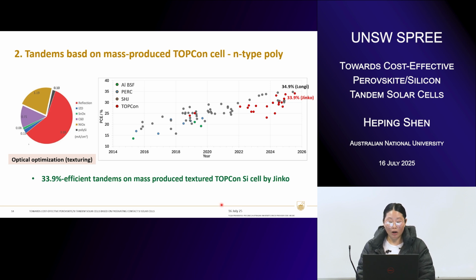simultaneously, we have been doing the optical optimization, particularly by using some texturing of the silicon substrate, majorly focusing on nano-texturing, which means texturing with a size of roughly 1 micrometer or less. For that we did a lot of work in collaboration with our industry partner Jinko, and I think that also allows further improvement of the cell performance. That is reflected by the recent record efficiency by Jinko using tandem based on TOPCon, which is up to 33.9% efficiency. Okay, so I believe there's still a good room for further improvement of the cell performance based on mass-produced TOPCon. So hopefully we can see more progress very soon.